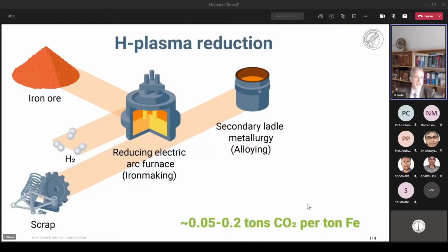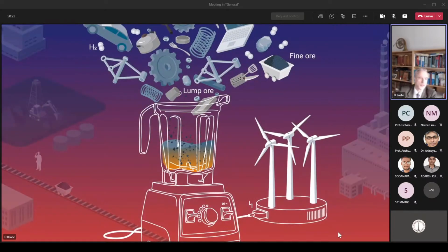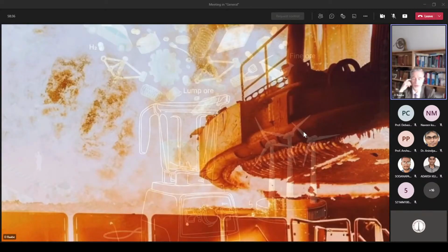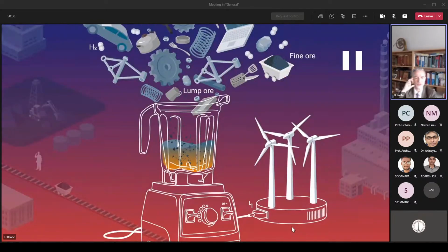So that is a scenario that has been tried out by only a few groups, when you operate a more or less conventional arc furnace, but you equip it with a small reduction atmosphere. And then you can arrive, depending on the quality of the electrodes, of course, and of additional fuels that you might use, with a very low carbon footprint. So I'm thinking of an aggregate like here that you can operate with sustainable electrical power, of course. After all, it's an electric arc furnace, so you directly use electric power. And that is really, really interesting in my view, because you don't need so much buffer energy like for the direct reduction techniques.